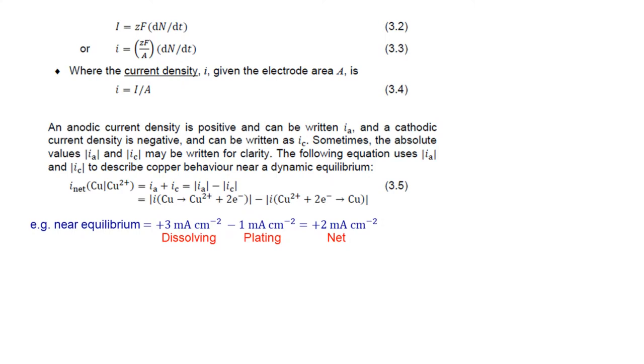Now, at this point, I want to point out that this relation in equation 3.3 describes the net current density of electrons flowing out of the metal anode. So this is an important thing to note, because in electrochemistry, many metal dissolution processes and similar processes are actually imagined as reversible things, in which there is simultaneously a forwards and a backwards process going on at the same time. And the net rate of dissolution of a metal is the difference between the forwards and the backwards rates.